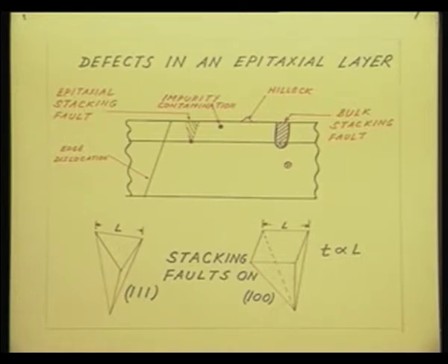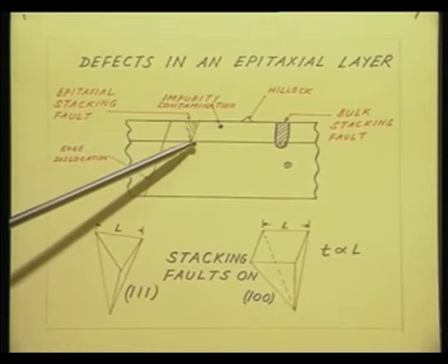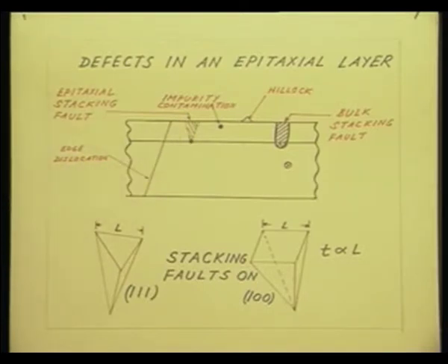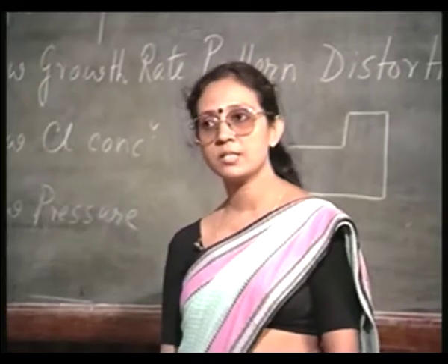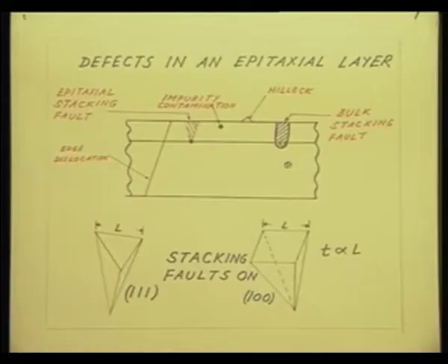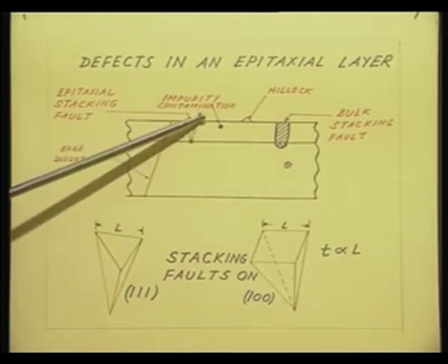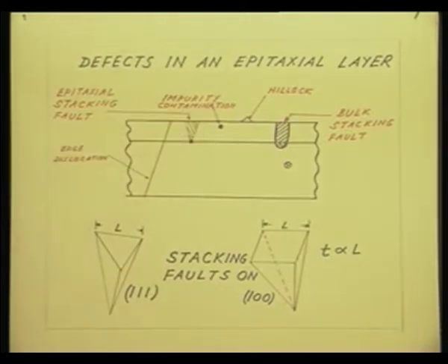Second point is, if there is something on the surface, that something most often is a small patch of native oxide, then a stacking fault may originate from that, and the stacking fault actually grows in size. As the epitaxial region grows, you see the area of the stacking fault is growing in size. We will discuss more about the stacking fault in a few minutes.